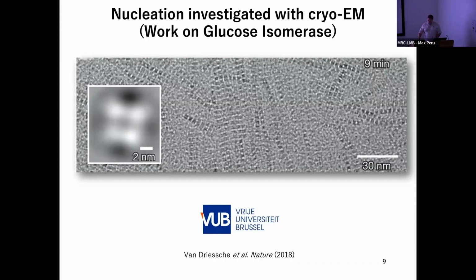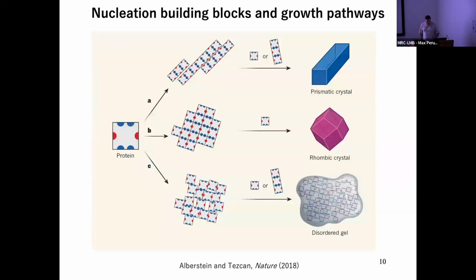But these groundbreaking works from the University of Brussels show that a main mechanism of nucleation is polymorphism selection that takes place at the earliest stages of nucleation. We could say it is based on specific building blocks. In fact, only a slight difference in the precipitant concentration means glucose isomerase can crystallize into at least two different space groups or can aggregate into a disordered gel state.